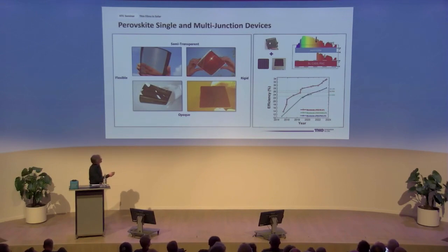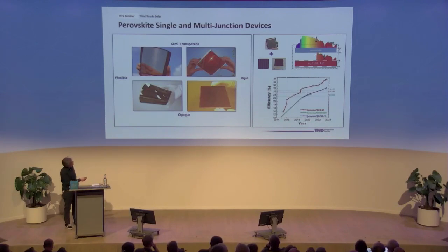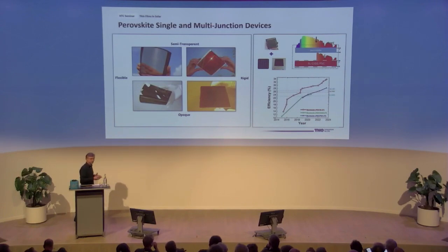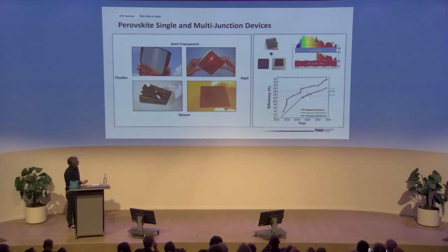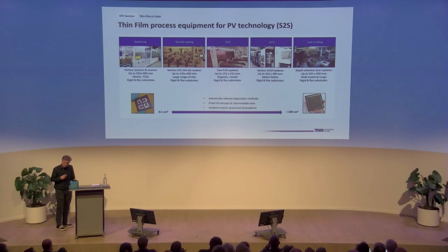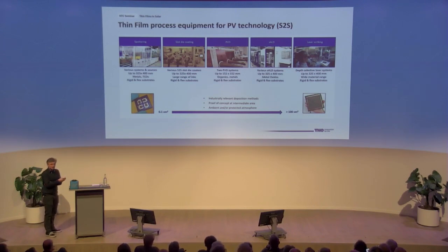As I mentioned, you can make a combination of perovskite and crystalline silicon to make a tandem device, and then the top cell, here the perovskite, absorbs more or less the blue part of the solar spectrum and transmits the infrared part of the solar spectrum. In this way you can achieve an efficiency that's a factor of 1.3 higher. And that is also what we see now in the lab. If we look at what's published in literature and what we measure in the lab, we see a strong increase in efficiency over time for this type of combination. But you can also make combinations of perovskite with perovskite. And that is this trend here, and now reaches about 29 to 30%. What's maybe interesting for the community here is that we have a wide range of tools that can be used to make thin layers.